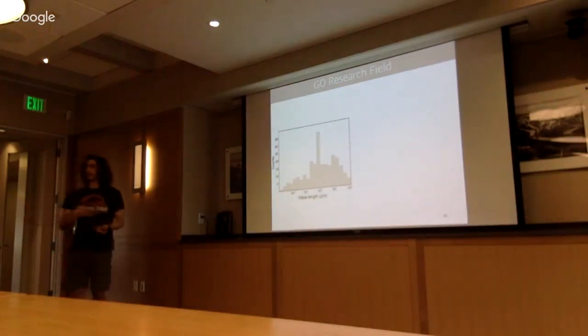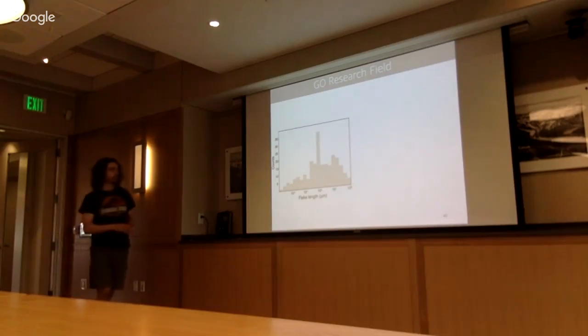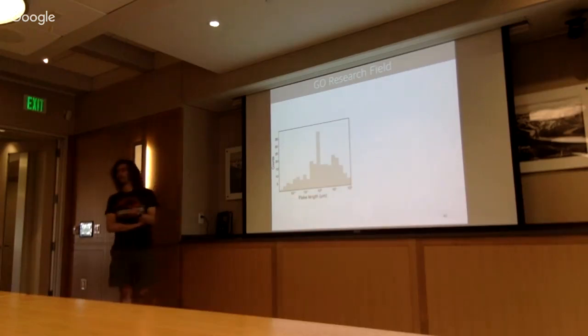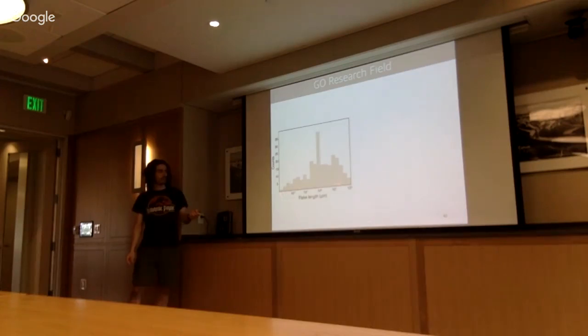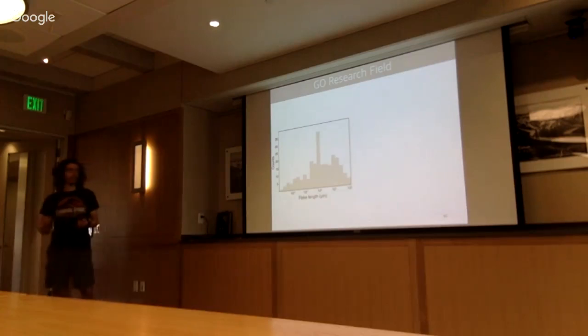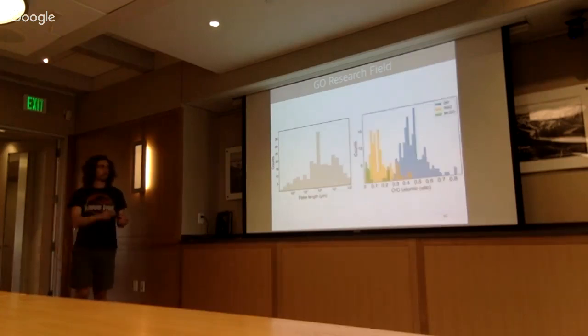And so here is an example of how we can use the morphology to create this beautiful architecture. Here what I did was compile all the studies of graphene oxide. Each of the counts is a scientific publication, depending on the flake size that the researchers were using. And you can see that the flake size varies by about 4 or 5 orders of magnitude in the dimension of flakes used by researchers.